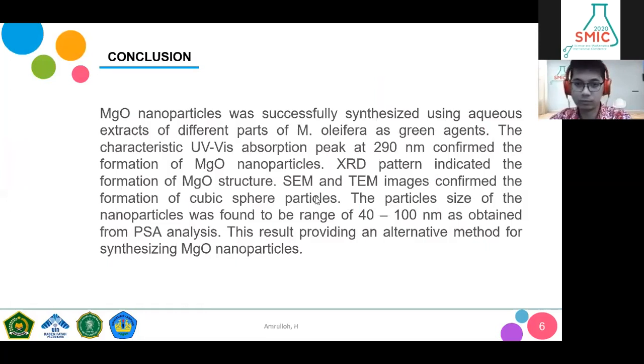as a green agent. The UV-visible absorption characteristic confirms the formation of magnesium oxide nanoparticles. X-ray diffraction pattern indicates the formation of magnesium oxide structure. SEM and TEM images confirm the formation of cubic spheres. And then the particle size of the nanoparticles was found to be in the range of 40 to 100 nanometers. This result provides an alternative method for synthesizing magnesium oxide nanoparticles.